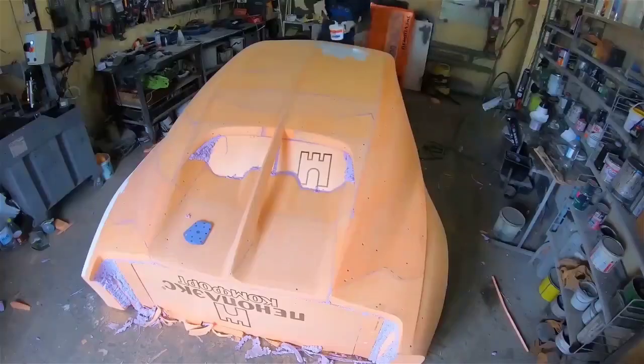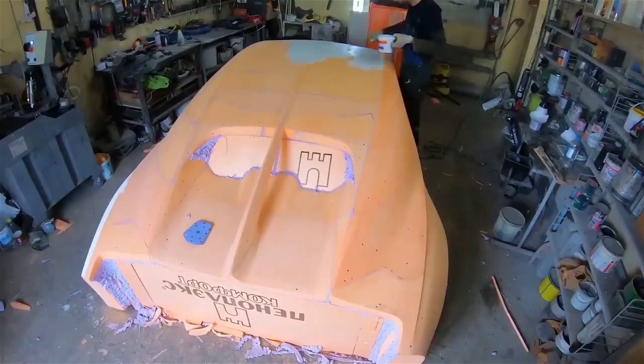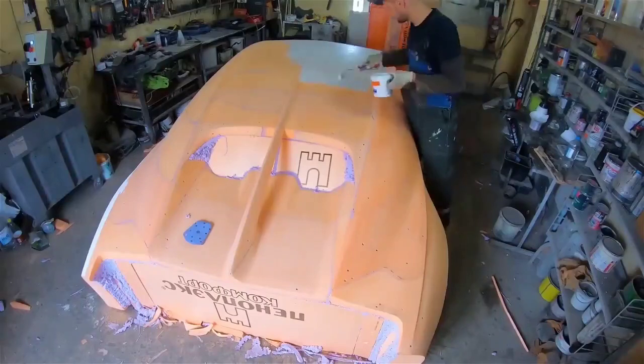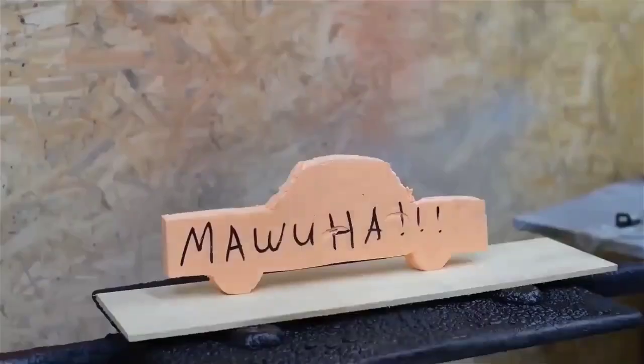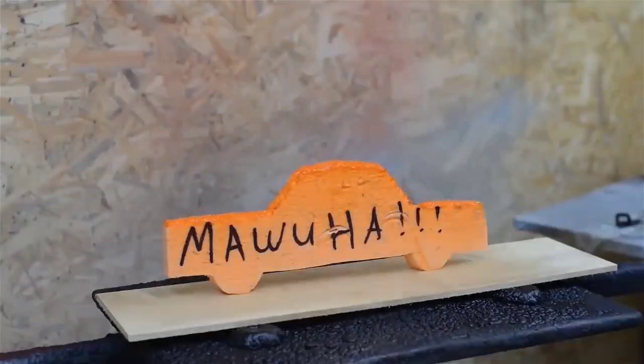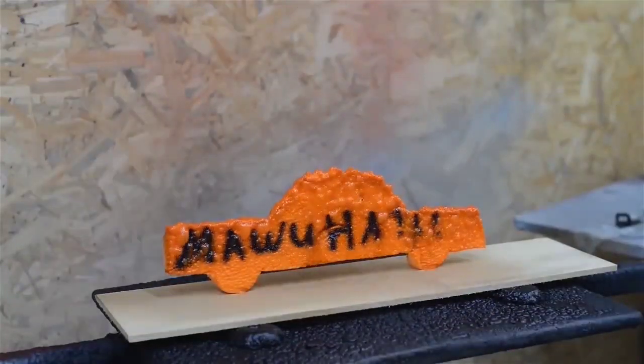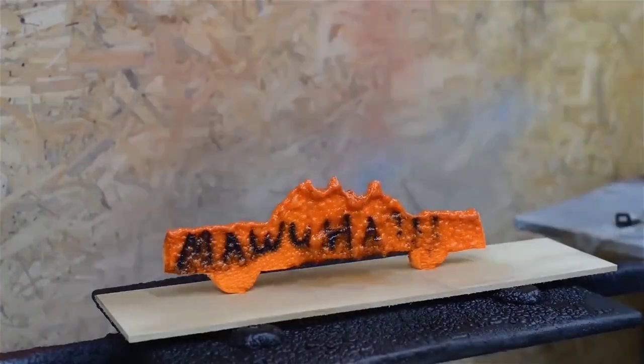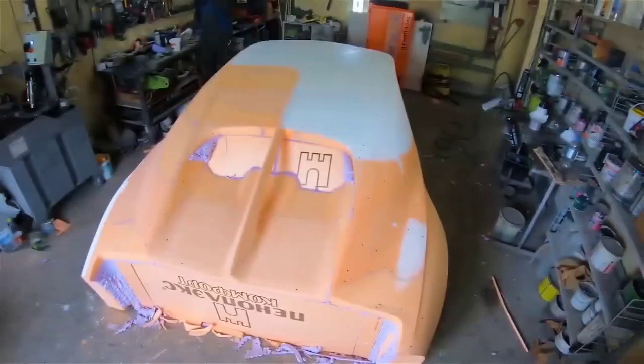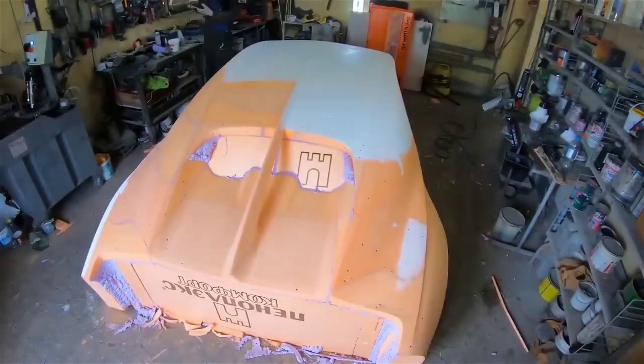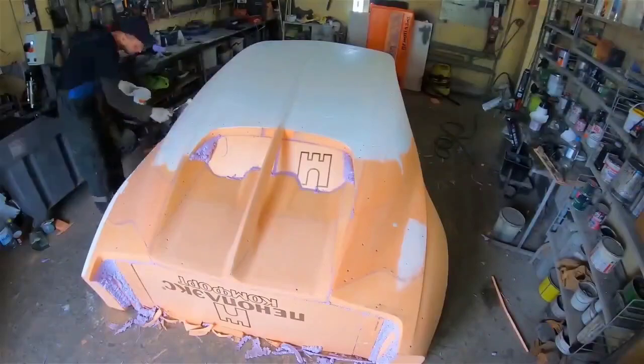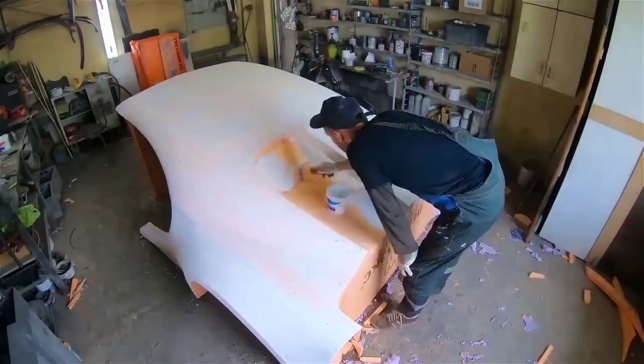Yes, the one that is used for painting walls, and this is important as any other resin or solvent-based material will ruthlessly corrode expanded polystyrene. Here's a good example. Just imagine, let's say you made a car body, cutting it out, gluing it, finishing it for a couple of months, and finally, the long-awaited final primer. You primed it, and after 15 minutes the body is gone. That is why at this stage we use water-based materials. In addition, they are much cheaper than professional 2-component materials, and they are just perfect for these purposes.